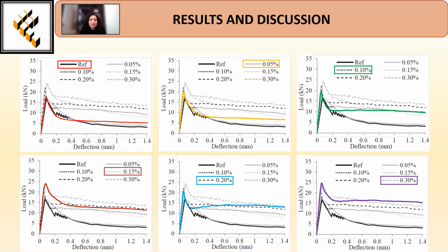In this slide are presented the results, so the comparison between the numerical load deflection curves, which are the colored ones, and the experimental curves, which are the black ones. We can see that the curves match almost perfectly in the first part, while some differences are present in the post-crack behavior, where a softening behavior is exhibited for low content of nanofillers, and a hardening behavior is observed when the content is higher than 0.1%.